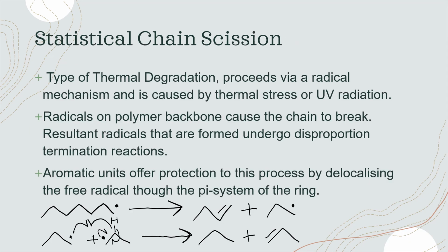Thermal degradation is the process where damaging chemical changes to the polymer take place at higher temperatures or when exposed to UV radiation. One type of thermal degradation is statistical chain scission, proceeding via a radical mechanism. During this process, radicals are formed on the polymer backbone either by hydrogen abstraction or side group elimination that can cause the polymer backbone to fragment. The formed radicals from this process are highly reactive and undergo disproportionation termination reactions. Aromatic units can offer protection against this because they can delocalize the free radical through the pi system of electrons, decreasing reactivity.